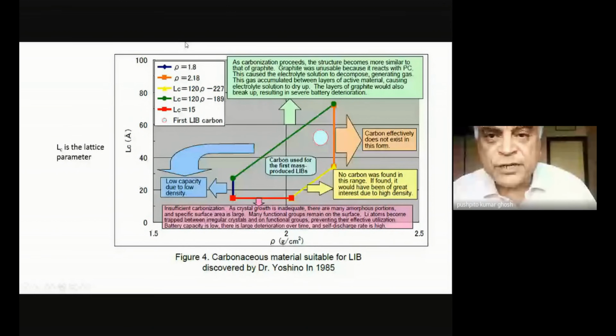As carbonization proceeds, the structure becomes more similar to that of graphite. Graphite was unusable because it reacts with propylene carbonate. This is the solvent. This caused the electrolyte solution to decompose, generating gas. This gas accumulated between layers of active material, causing electrolyte solution to dry up. The layers of graphite would also break up, resulting in severe battery deterioration.